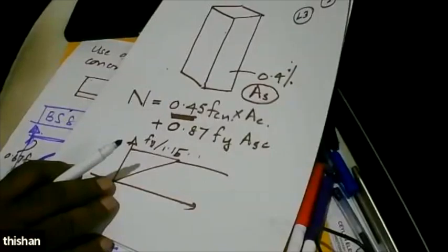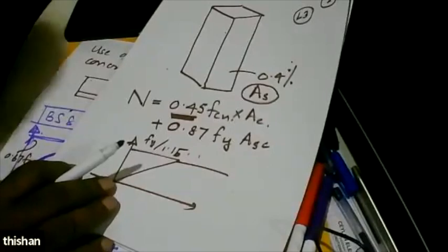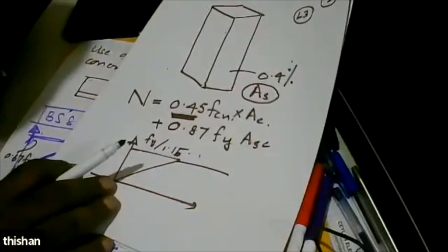But unfortunately, what we see today is, recently we have visited one school building, maybe 15 years old, but already columns have started deterioration. One is poor quality concrete with very little aggregates. Second, they are not cured. They have cured everything else except the columns. Whereas we have to understand column is the key element in a building. And column is the one that is heavily loaded. So it has a small cross-section and a heavy load. You must pay a lot of attention to columns.